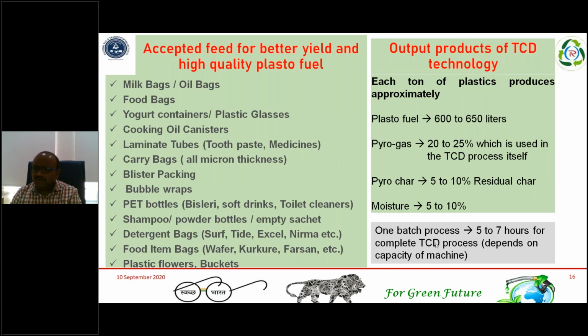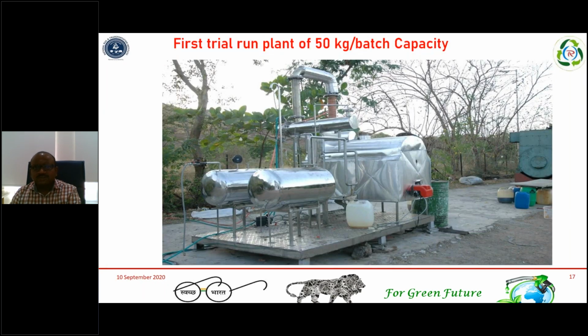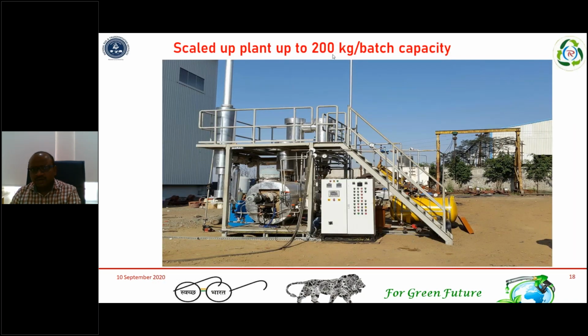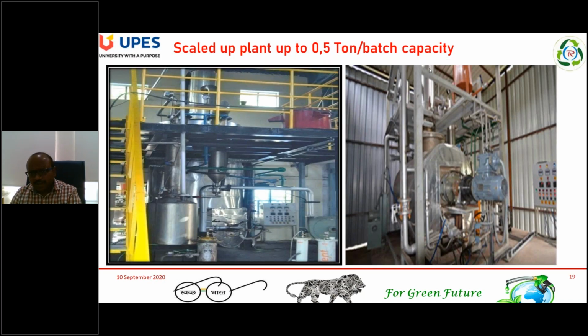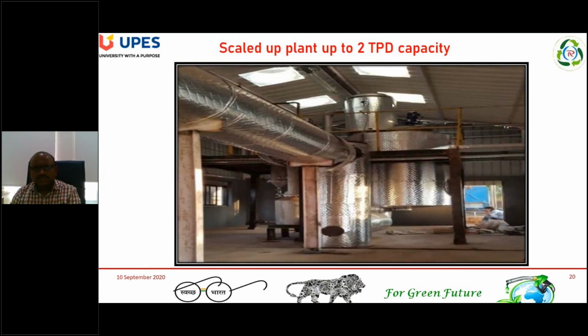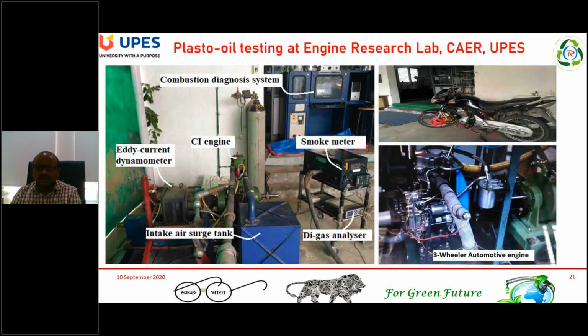Now we have developed the continuous pyrolysis technology, continuous TCD technologies, for which we have applied to DST for funding. This was the first machine, the first plant that we set up during early stages, with 50 kg per batch pyrolysis plant, TCD plant in Pune. And this is the second upgraded one, which treats 200 kg per batch. And this is a 0.5 ton per batch capacity plant. And this is the plant which processes 2 tons per day. Now we have submitted the proposal for 10 tons per day of continuous.